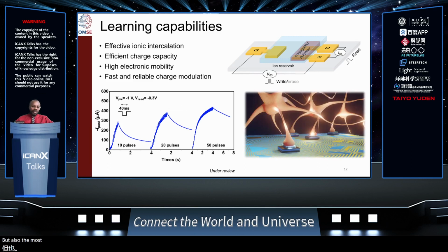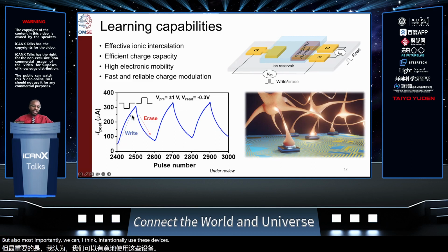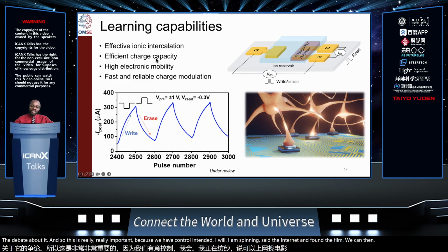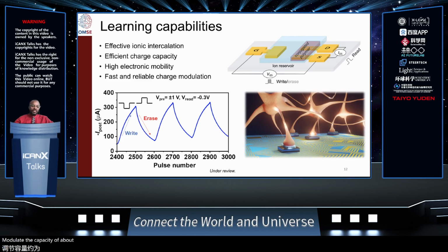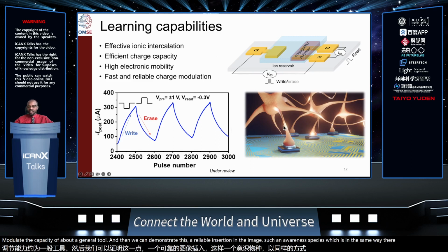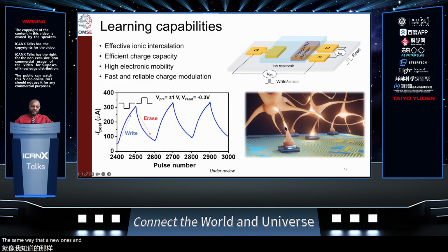But also, most importantly, we can actually intentionally use these devices for the learning and forgetting properties that we find in the body. How we do it here, we're applying a series of pulses in one direction, and we can erase that memory by applying opposite polarity of the gate voltage. This is really important because we have control in terms of how well ions can intercalate into our polymer film. We can then modulate the capacity of our channel material, and then we can demonstrate this reliable insertion and extraction of ionic species, which is the same way that our neurons and synapses communicate.